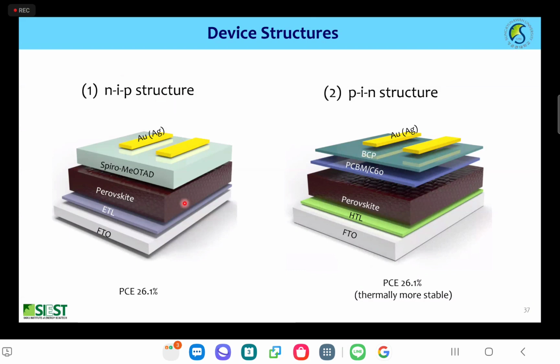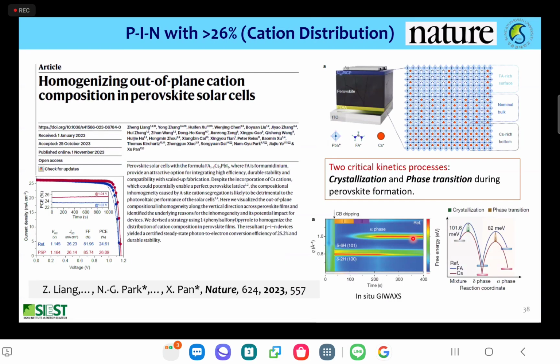This is high efficiency, but the stability is not good. But the PIN structure is regarded as the stable configuration, but efficiency was lower than the NIP structure so far. But recently, the PIN structure efficiency achieved over 26%. Here is a very interesting result.